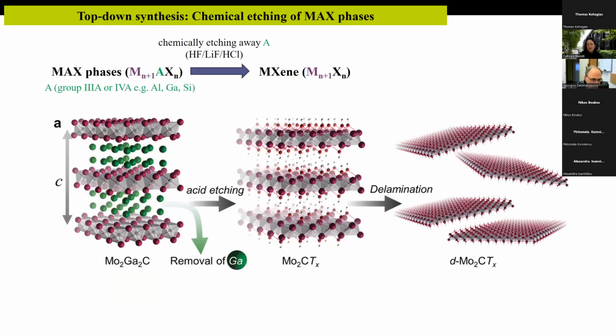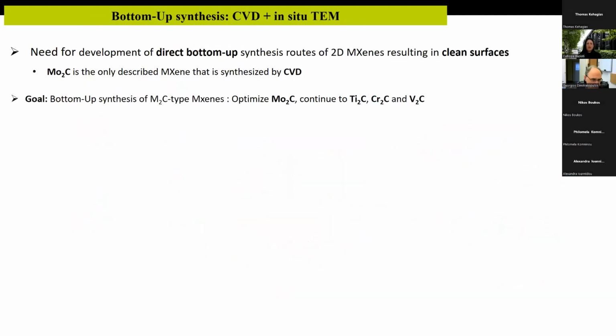The problem with MXenes is their synthesis route. So far, they are developed only by top-down synthesis by chemical etching. Basically, they etch away the metallic layers of their MAX phases. But this process results in residual surface terminations of functional groups. This is an unavoidable byproduct of the etching process, and it has, unfortunately, a detrimental impact on the properties of this material as an anode for batteries.